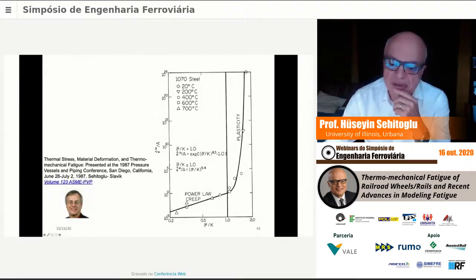And so this is stress, it's normalized. This is inelastic strain rate. This is the power law creep regime, where if you change the strain rate, there's a lot of sensitivity to the strain rate. The stress changes quite a bit. This is the plasticity regime here. That's at lower temperatures and higher strain rates, where if you jump the strain rate, the stress doesn't change very much. So there are different equations, of course, for this.